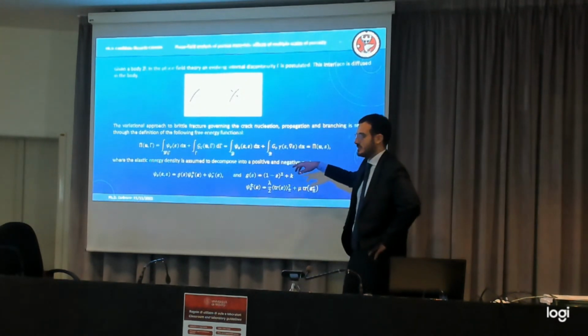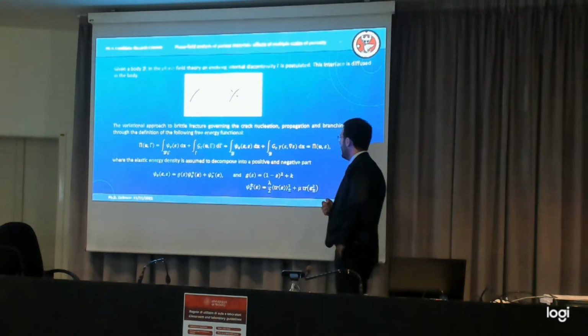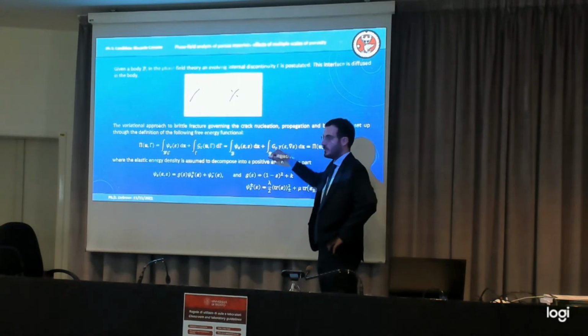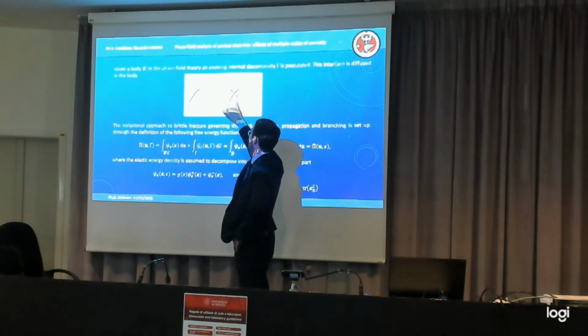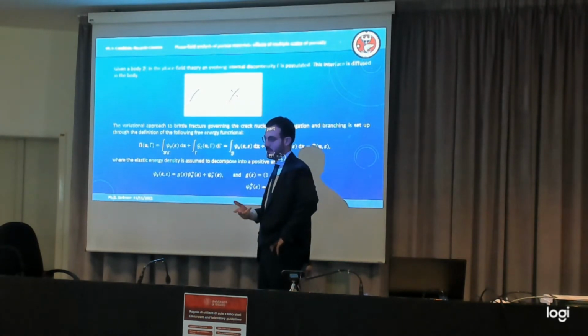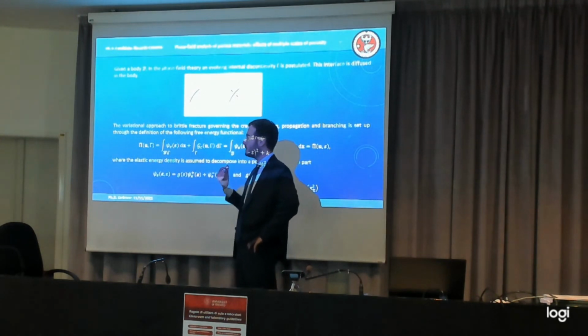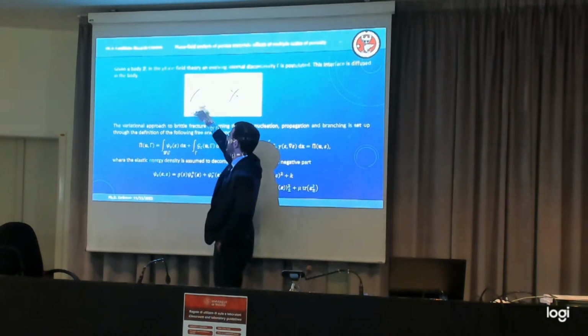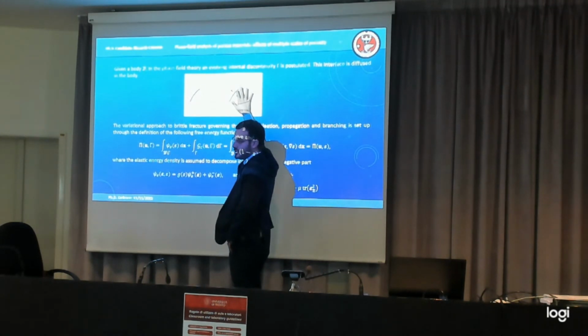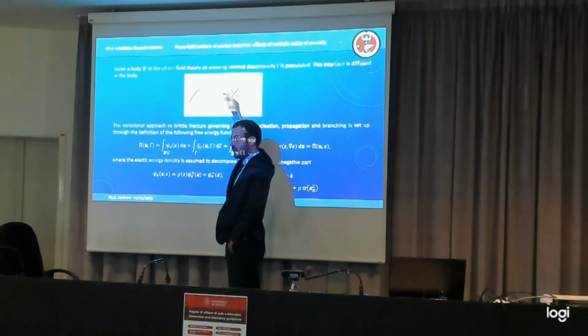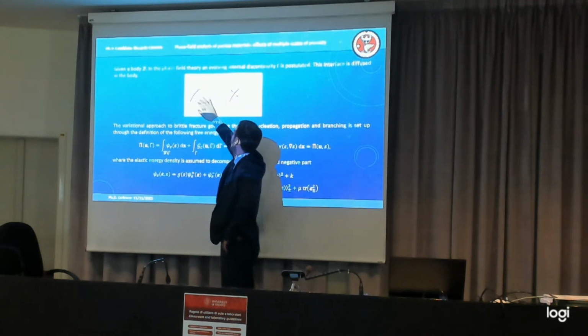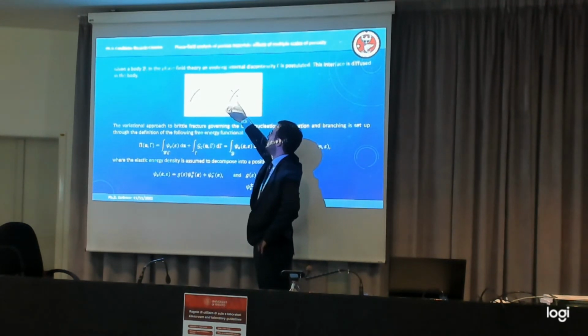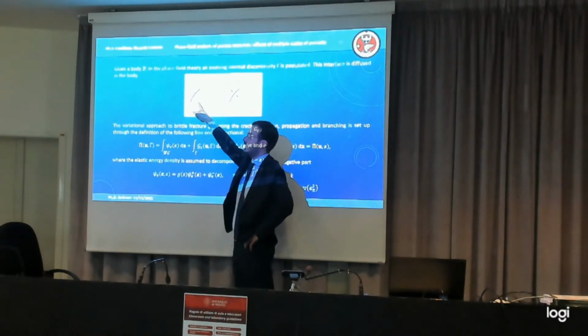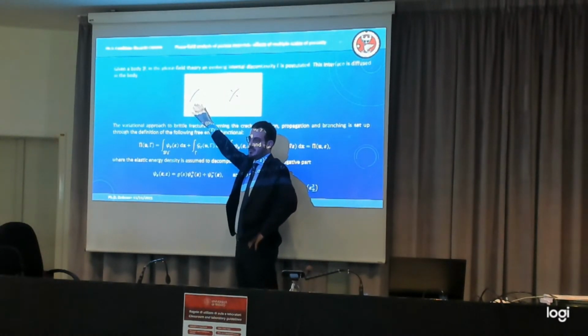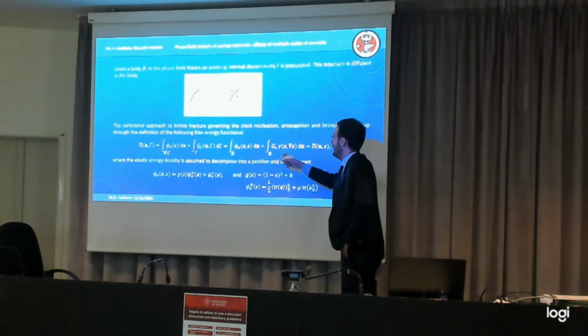the fracture energy. This is the fracture energy intended in a Griffith sense. And so you need to calibrate this. This is the first one. The second one is represented by this L over here. It's the regularization parameter, and basically, when you do the topological approximation, I said that the crack is no more a crack, but it's a diffusive damage. The more this regularization parameter is sent to zero, the more the damage volume converges to a line damage. So the regularization parameter is giving you the accuracy of the model with respect to the classical solution. This is the second parameter, so L and G_c.